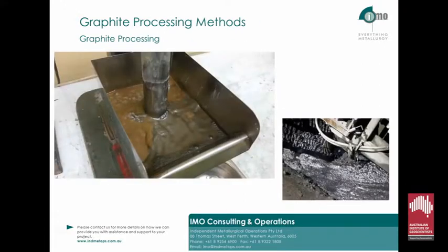Flotation of graphite is the traditional method used to upgrade graphite, and ultimately it's the only way to determine the final flake content and grade of a graphite sample. Characterising the sample by either a size by assay on the feed or using various petrology techniques such as SEM are a good indicator, but it will not give you the final answer.